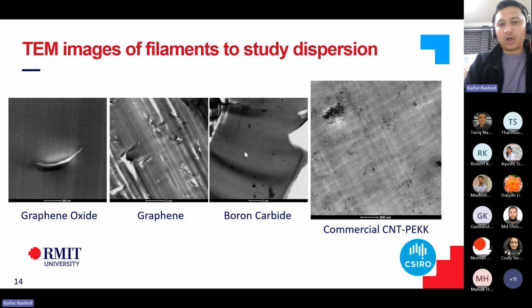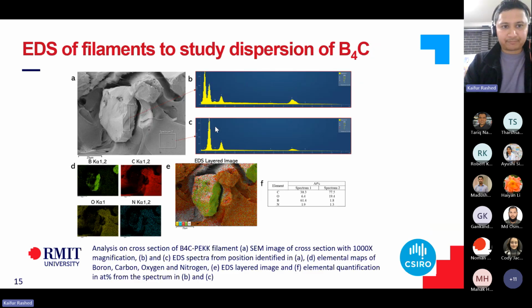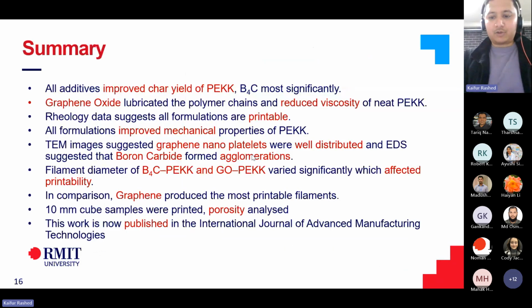And this is the commercial CNT-PEKK. So this one also shows good distribution, but it also has agglomeration as well. So then I studied EDS to determine if there's any agglomeration of boron carbide, and I saw, yes, boron carbide was significantly agglomerated, and that caused issues with feeding as well. So when I fed them into the printer, parts were starting to wear off very quickly because of the hardness of boron carbide again. So conscious of time here, I'm just running quickly through the slides.